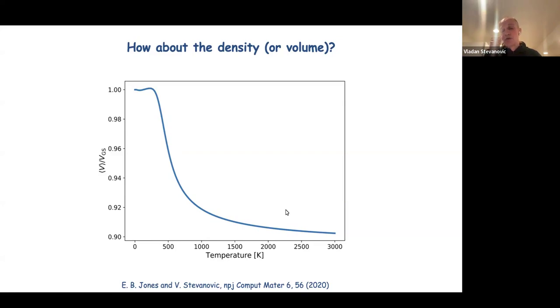And by the way, that's a consequence of the distribution tilting to lower densities, if you remember that discussion. So for silicon, all those points were tilting to denser structures than the diamond. So the mixture will then have, as an average, lower volume. And we then went and found the experimental result for liquid silicon. Liquid silicon is known for the same anomaly as water, that liquid silicon is actually denser than the crystalline phase. The same ratio from experimental results, the volume of the liquid divided by the volume of the crystalline phase, where the volume of the liquid is taken at the melting point, corresponds to about 1%